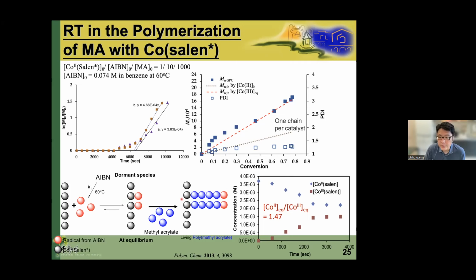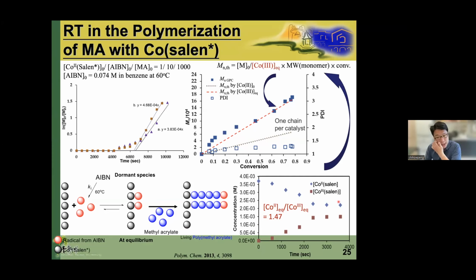cobalt species. So by using the UV spectrum, we follow the change of cobalt-2 concentration and the cobalt-3 concentration, and we obtain at the equilibrium, the ratio of cobalt-3 is 1.47. And so we recalculate the theoretical molecular weight based on one chain per cobalt-3. And at this time, we found the theoretical molecular weight matches the experimental value now. So why is there this difference? In vinyl acetate, all cobalt-2 converted to organocobalt-3, but in methyl acrylate, only part of the cobalt-2 converted to organocobalt-3.